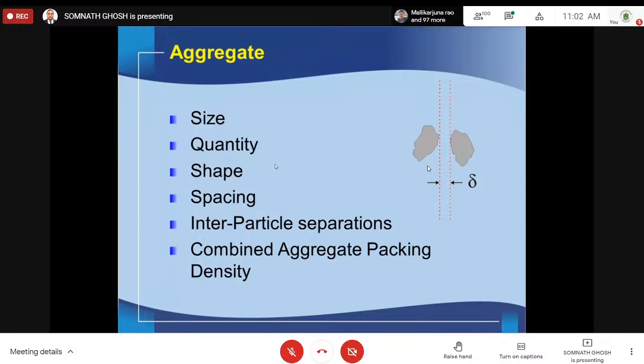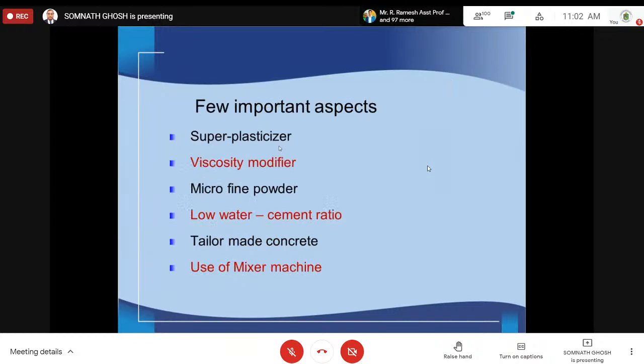Normally, we are not really discussing or understanding or using these things properly. Now, these are the very important aspects. Superplasticizer, obviously, high range water reducing superplasticizer, viscosity modifier, microfine particles like silica fumes, fly ash, etc. Low water cement ratio. If you go for high water cement ratio, you will not be able to achieve self-compacting concrete. It's a tailor-made concrete. Why tailor-made? Because your client may ask for a particular strength, particular workability, particular durability, and many other aspects, pumpability, and you have to develop accordingly.